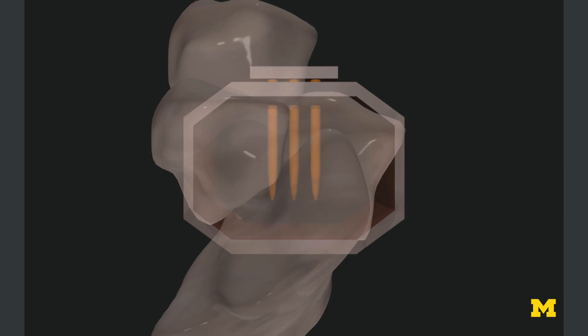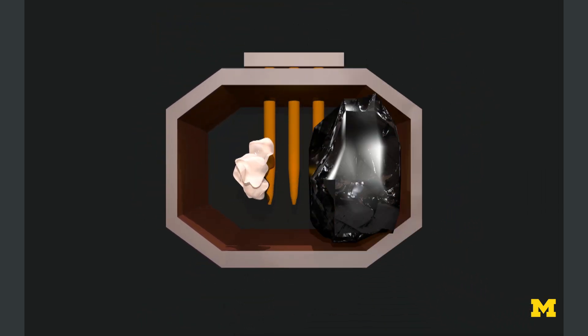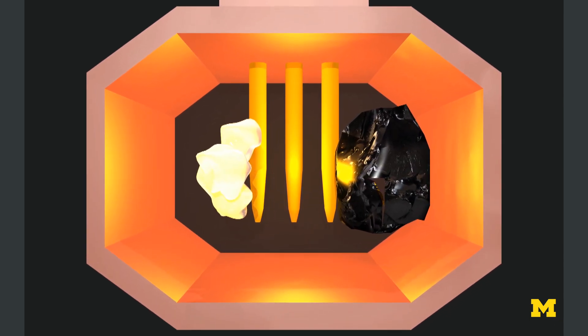But they all are built on the use of silicon metal. That's done by taking silica with carbon and treating it in an electric arc furnace at 3,000 degrees Fahrenheit. By producing silicon that way, you also, of course, produce carbon dioxide.